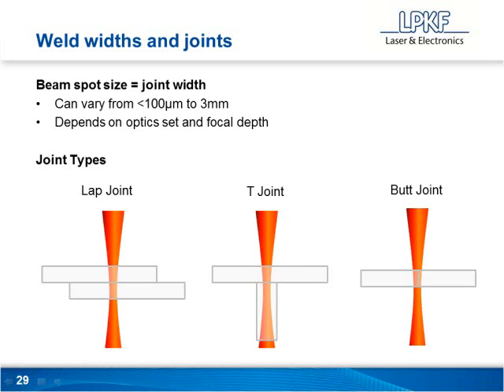And that's because, recall, we need to maintain contact between the 2 pieces. So in order to do that, if we can press them together effectively, then we can get nice contact between the 2 parts. So rigid's naturally going to be easier to do that with from a fixed strain standpoint. Secondly, because the laser is passing through and volumetrically heating both parts, as you can see here on this butt joint, we're getting melt throughout the whole piece,